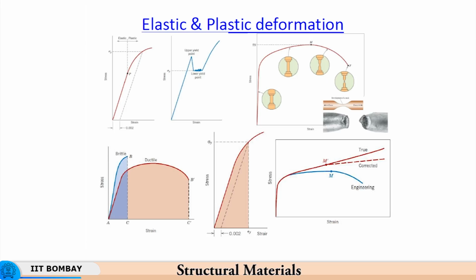Now, if you take materials like silicon carbide, which are not ductile, which do not undergo plastic deformation, which are brittle for example, you will not see this cup and cone type of fracture, because the features which develop as a fibrous zone will not be developed, because there has been no plastic deformation before failure. We will see in subsequent classes on fracture how ductility influences the appearance of the fracture, but then you have ductile fracture where significant plastic deformation has been undergone by the material.